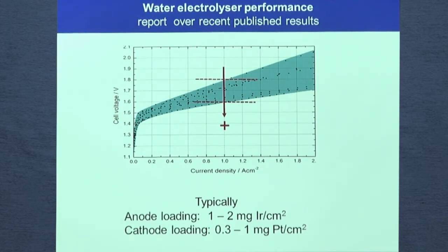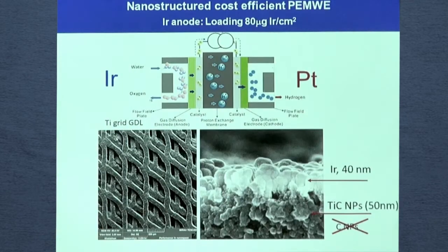So what is published lies somewhere in between these two borderlines, and the typical anode loading where iridium is used is 1 to 2 milligrams of iridium per square centimeter. We are using a certain deposition again. We are depositing iridium at the surface, but of course we cannot use carbon nanoparticles here because of the highly oxidative potential. We are replacing carbon nanoparticles by titanium carbide, which is very well conductive and much more stable at the high oxidative potential.